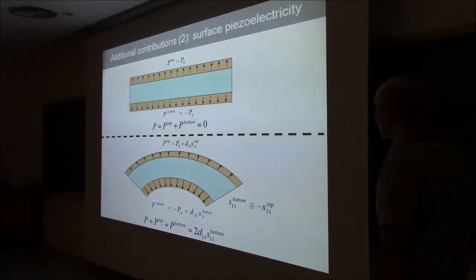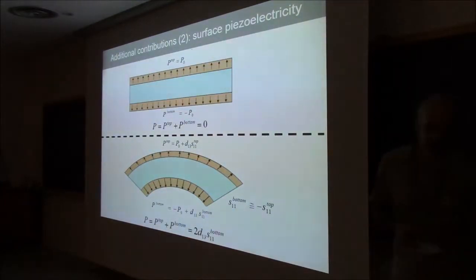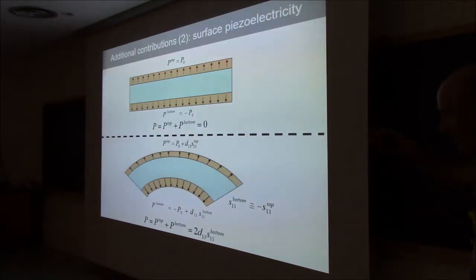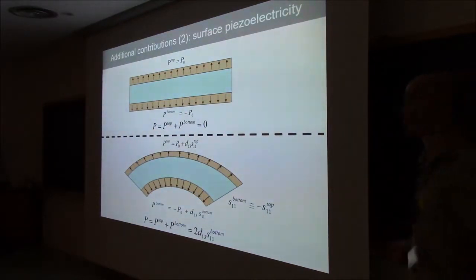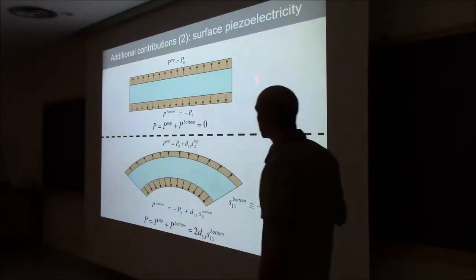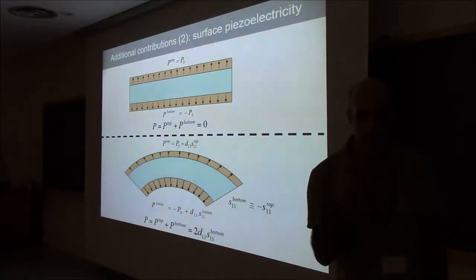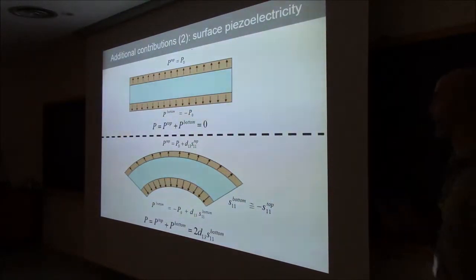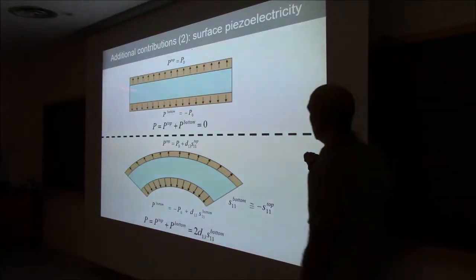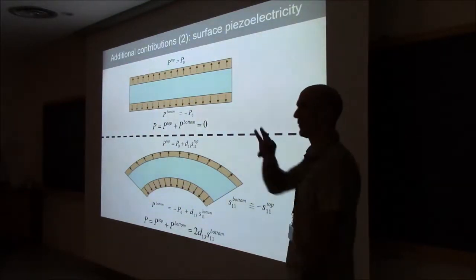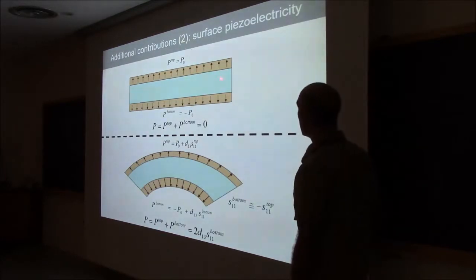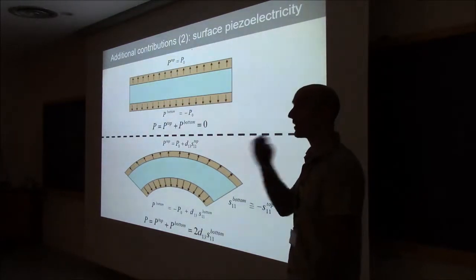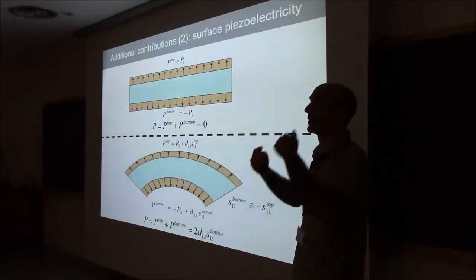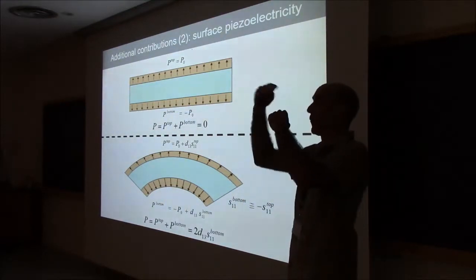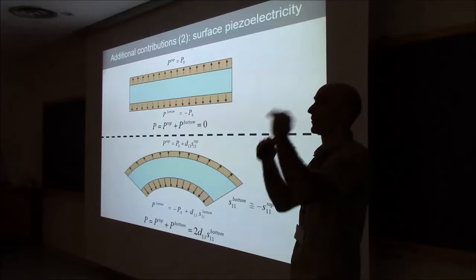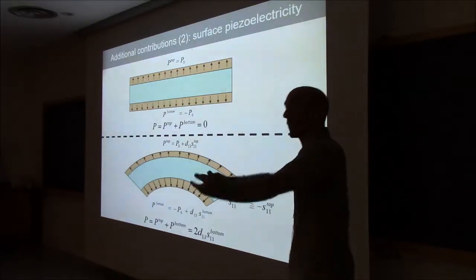Okay. So I mentioned intrinsic flexoelectricity, then fake flexoelectricity that comes from piezoelectric contributions. There's another piezoelectric contribution that is not fake. This one really is there all the time, and it goes like so. If you have any material, even a perfectly centrosymmetric material, the surface of the material is necessarily piezoelectric, in the sense that it's not centrosymmetric. What you have above the surface is different from what you have below the surface. Therefore, it's not centrosymmetric, and therefore it's piezoelectric.